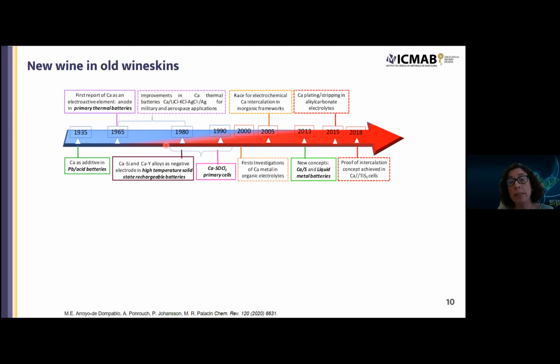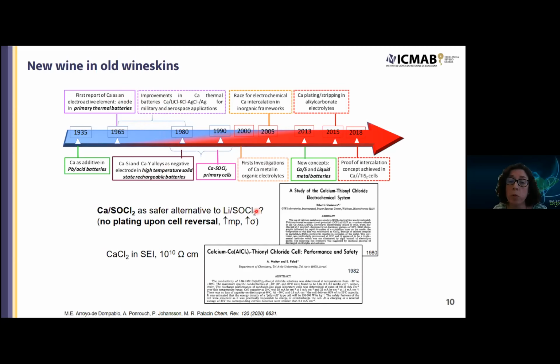Then in the 90s, there were studies by the group of Emmanuel Pellet and Israel and Staniewicz in the US, aiming at substituting lithium anodes in the lithium thionyl chloride technology by calcium as a safer alternative. So calcium would have a higher melting point and also a higher conductivity. And the main issue would be that upon cell reversal, there will be no calcium plating. So it would be safer, and the reason why no calcium plating takes place was thought to be that the SEI in this technology consists of calcium chloride, and this does not enable transport of calcium ions.